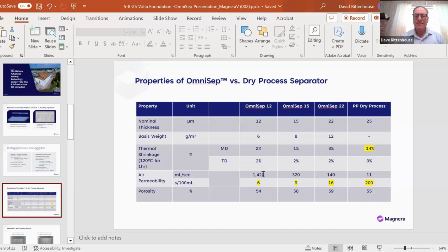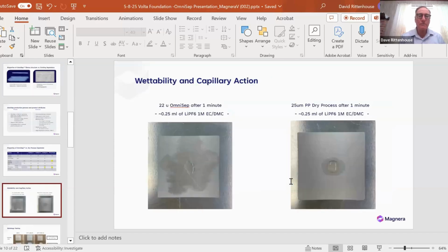We use a different testing method called the Textest, which is common in the textile and nonwoven market. That gives us a better range of relevant numbers. You can see how the number is very low compared to our extremely high porosity and airflow. What's interesting, and the reason that I pointed out these rungs or areas of crystallinity in the stretched film, is that on a calculated basis, the porosity, which is basically the density or amount of void volume, is not that far off in comparison to the actual airflow rates or electrolyte flow capability.